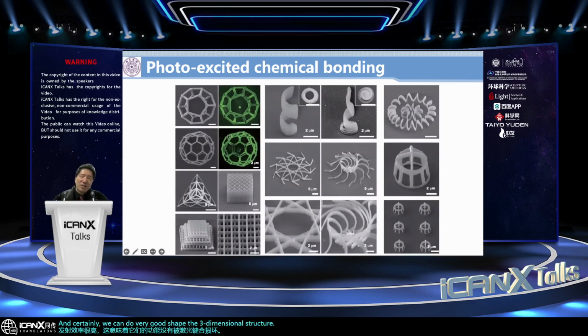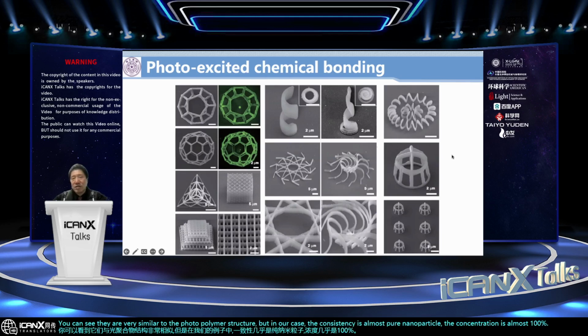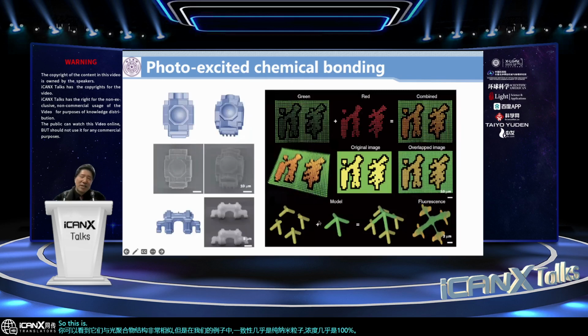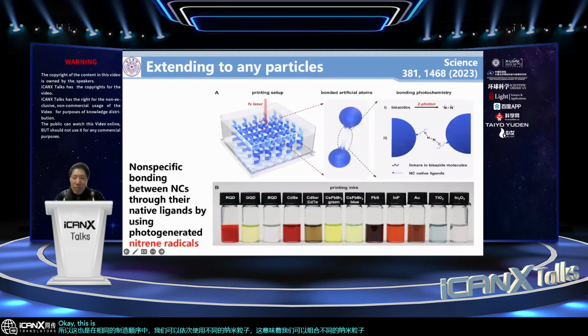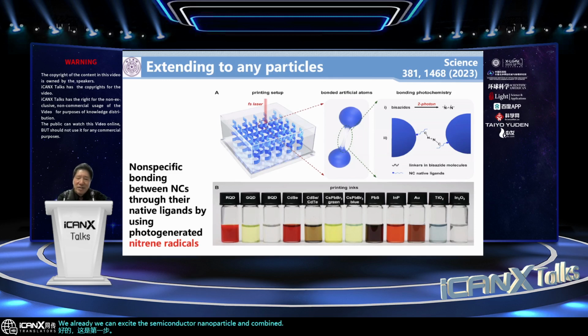Actually, just to see the surface, you can see they are very similar to the photopolymer structure, but in our case, they consist of almost pure nanoparticle. The concentration is almost 100%. So in the same sequence of fabrication, we can sequentially use different nanoparticles. That means we can combine different nanoparticles in one structure. Okay, this is the first step. We can excite the semiconductor nanoparticle and combine and assemble them into 3 dimensions.